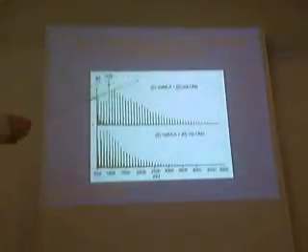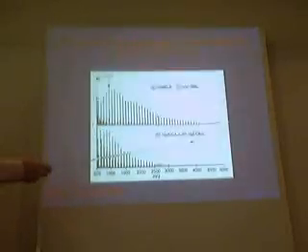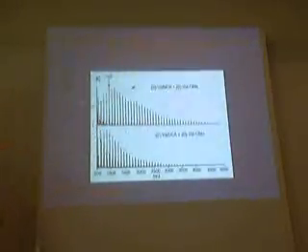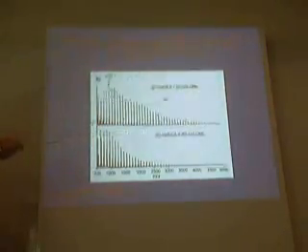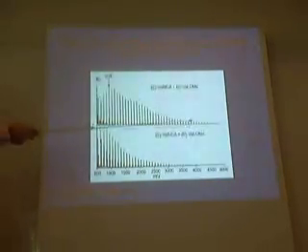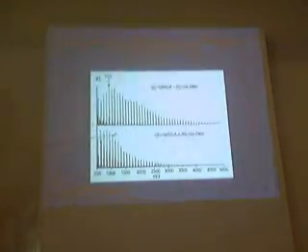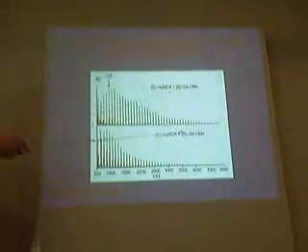If you go to solution and polymerize S-valine with L-methyl ester and S-valine with R-methyl ester, here you have to form the pleated sheet, because you don't have any other alternative. If you compute the enantiomeric excess, normalized to one of the big peaks, you can see that the enantiomeric excess here is in favor of the S, compared with when it was done with the R enantiomer.